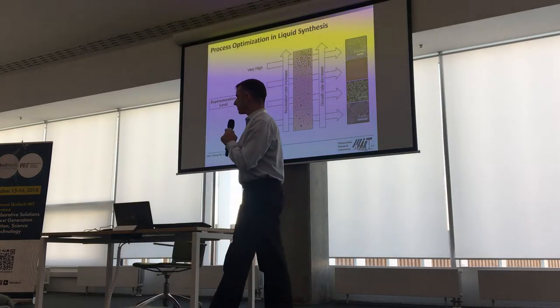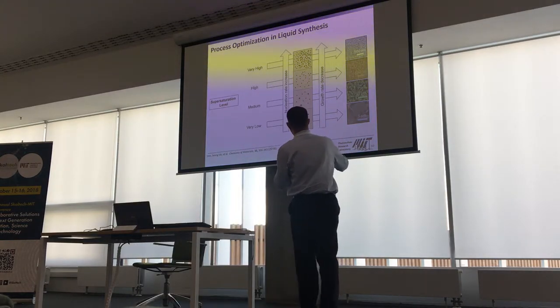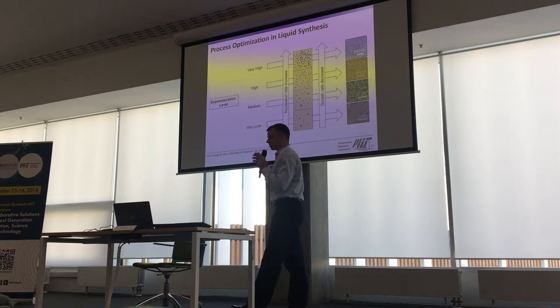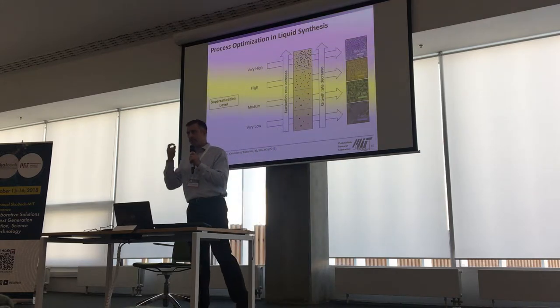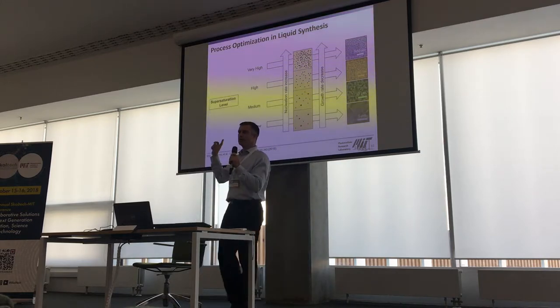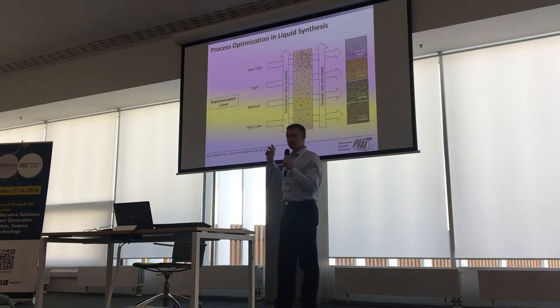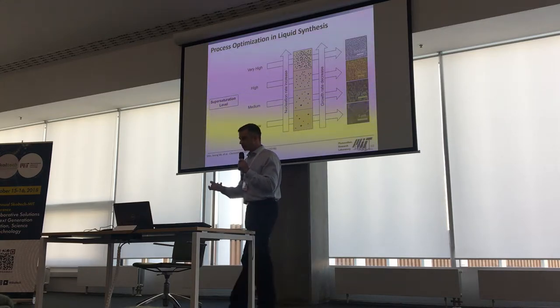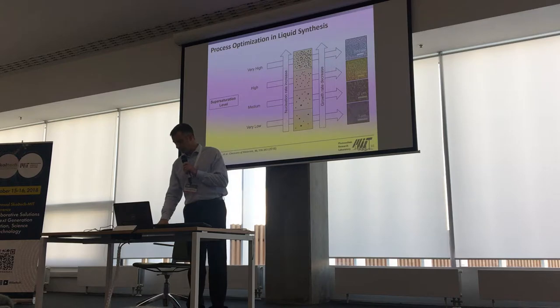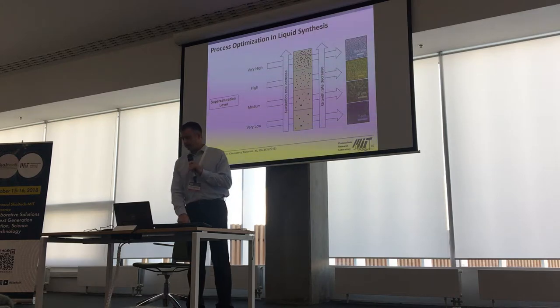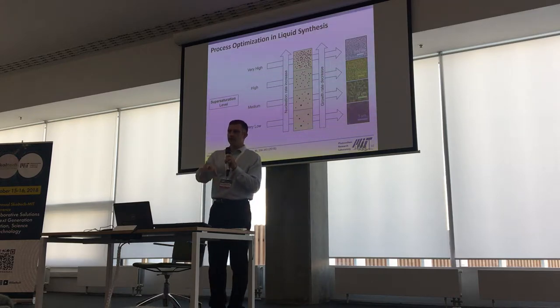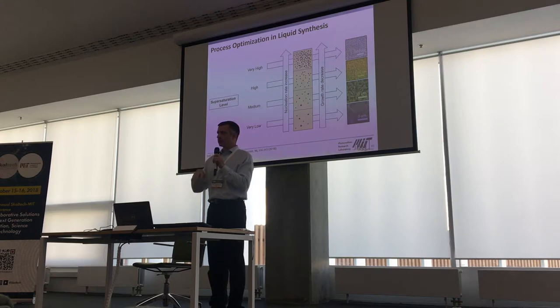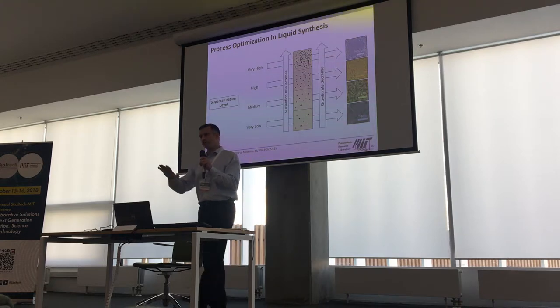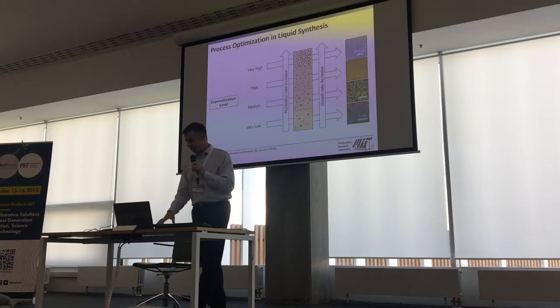And depending on the rate of solvent extraction and the addition of what's called an anti-solvent to precipitate the bismuth out of solution, you can control film morphology, and you can control the nucleation behavior of this material. In the course of designing these precursors, we were putting together a library of elements that we could access, and a library of process conditions so that we could achieve the right morphology of our films, contiguous films, for example.